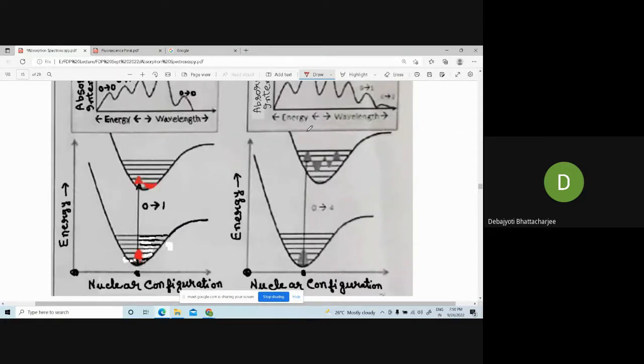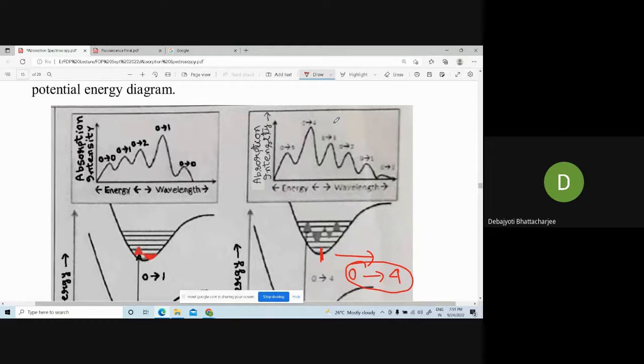And similarly, in this case, you see, due to deformation of the excited electronic state, or deformation of the molecular structure, or aggregation of molecular structure, or formation of dimers or trimers, etc., a lot of things may happen. And this excited electronic state is shifted to the right side, so that this position does not match exactly with this position. And as a result, when this electronic transition takes place from the ground state, it goes to the 4th vibrational level of the excited electronic state, and therefore this 0-4 transition occurs. This is the most probable transition. We say this 0-4 transition is the intense vibrational peak, and it will occur here. Other vibrational peaks have less intensity.